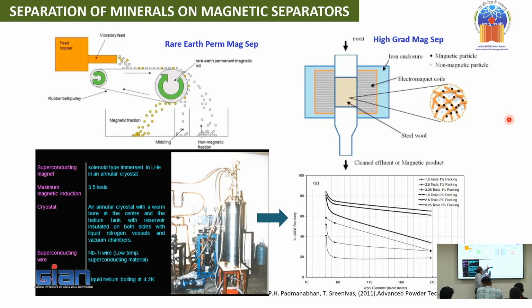Now here you can see the development. Even in these high gradient magnets, once you increase the current, the resistance also increases. So what happens is the effectiveness will come down after a certain stage. There comes the superconducting high gradient magnetic separator. Here we use superconducting wires like niobium tin, niobium titanium. These are some of the superconducting wires which I have shown you. This will be able to give a field strength of 3.5 Tesla. To that extent, it can give the field.